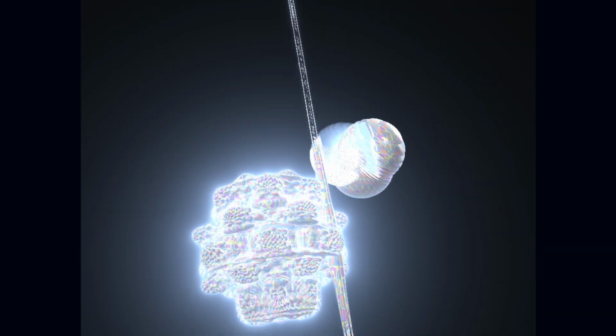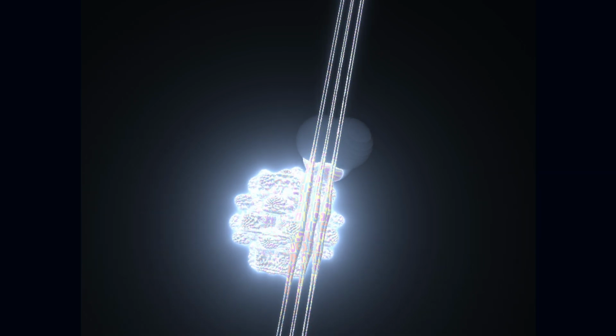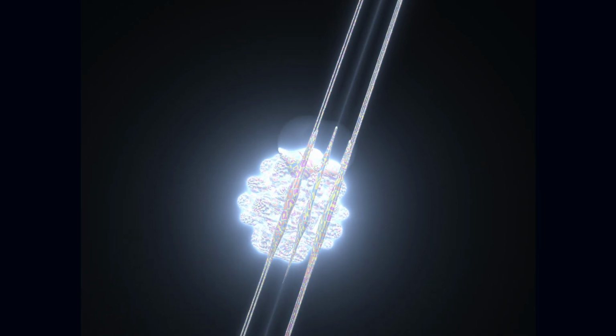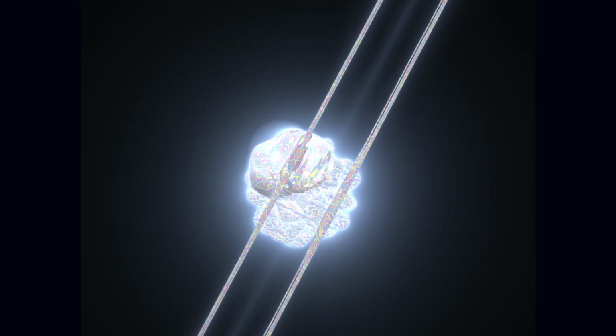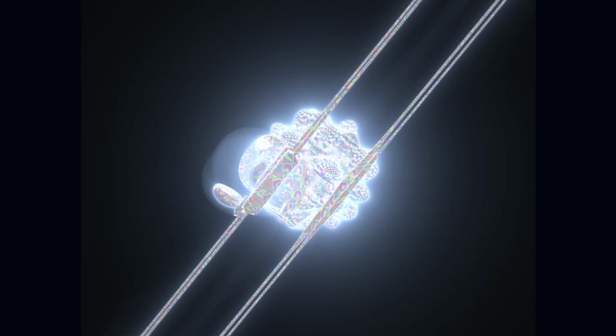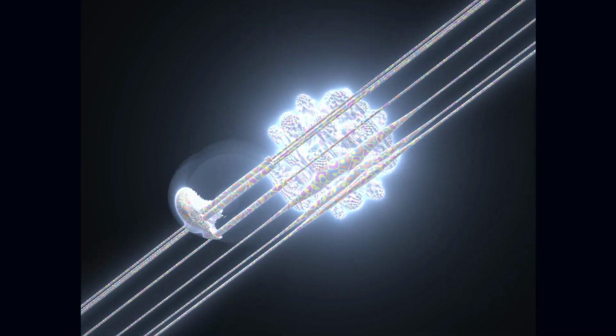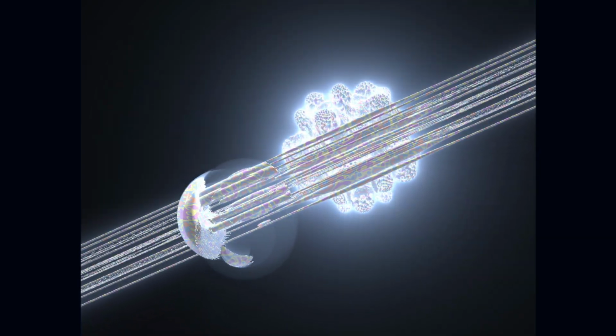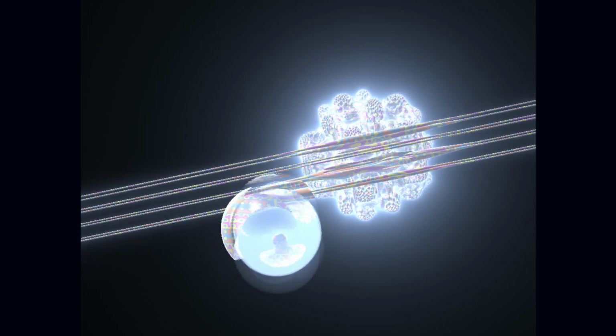Interesting. And different phonon modes matter too. Hugely. Different phonon modes can couple with vastly different strengths. In CsPbBr3, for instance, specific lead-bromine stretching modes couple to electrons about two orders of magnitude stronger than other phonon modes. Wow, 100 times stronger. Yeah. So this means that certain specific lattice vibrations can truly dominate a material's electronic properties.